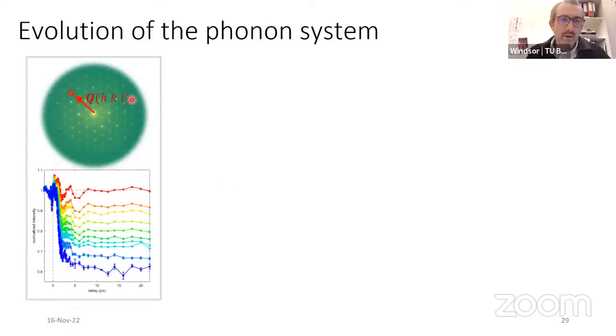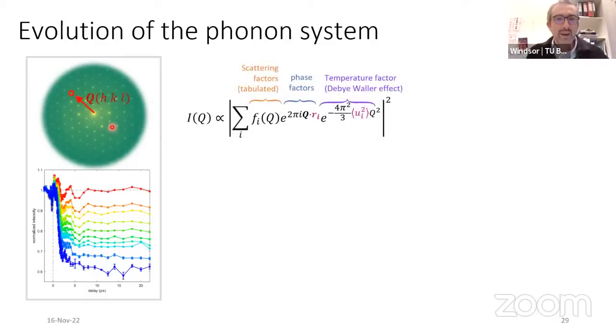So if we think of our data, this is essentially the data I just showed you. One of the greatest powers of diffraction is that it is very deterministic compared to many other experiments. What I mean by this is that every single Bragg peak's intensity can be described analytically with a structure factor like shown here. This is a sum over every ion in the unit cell. And there are three terms here.